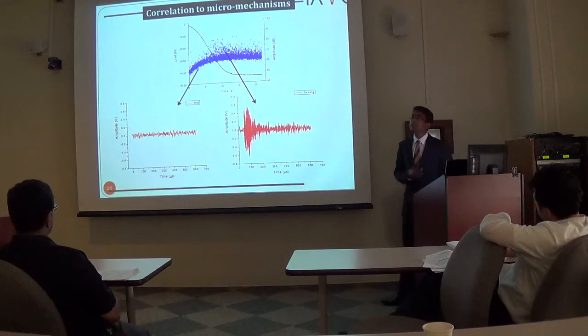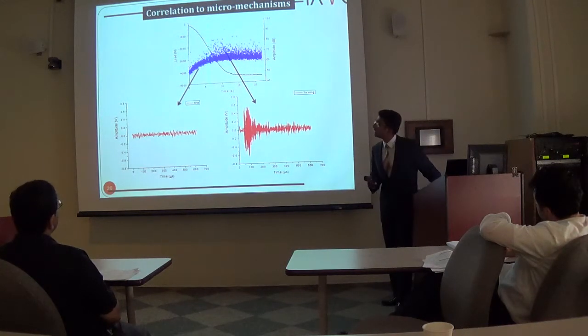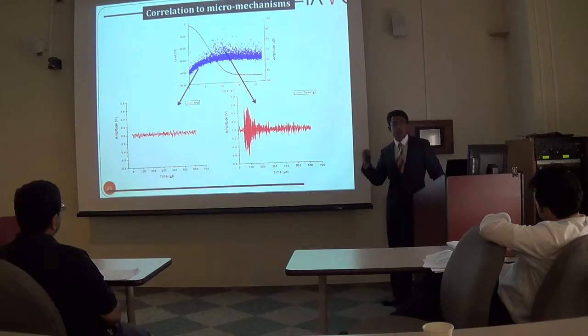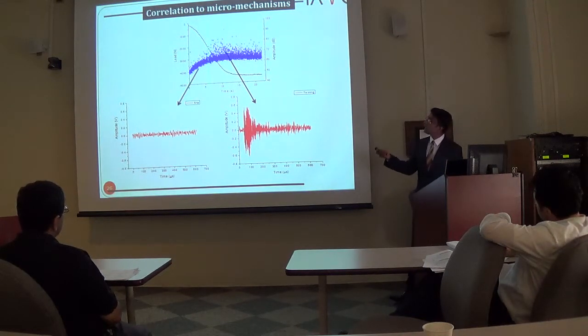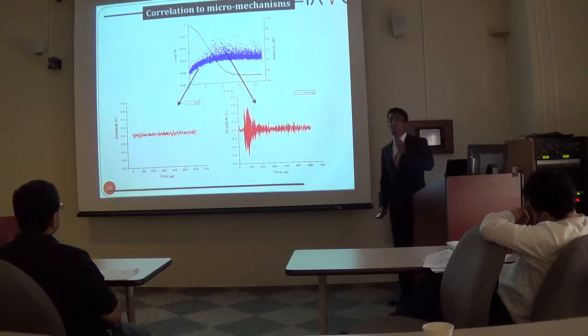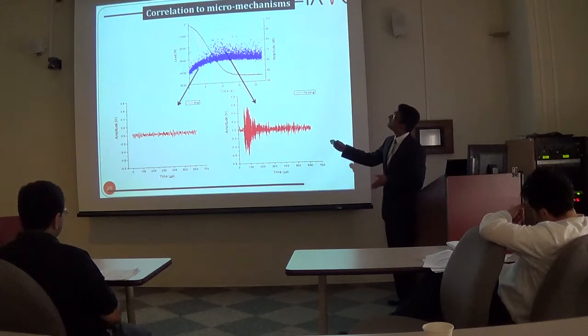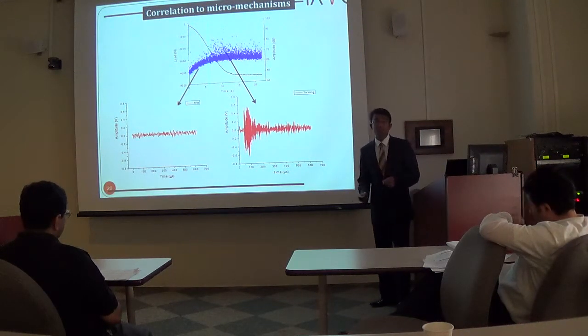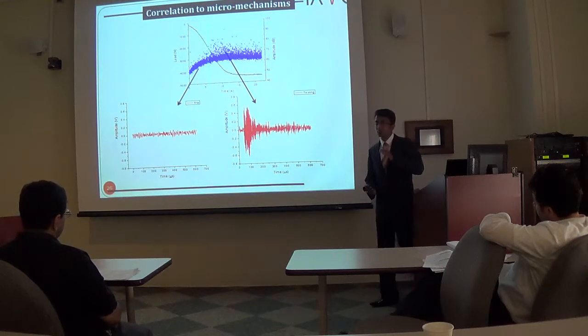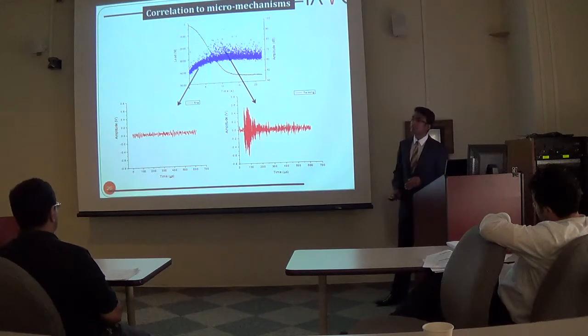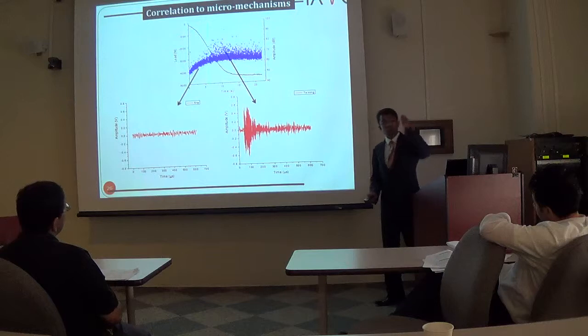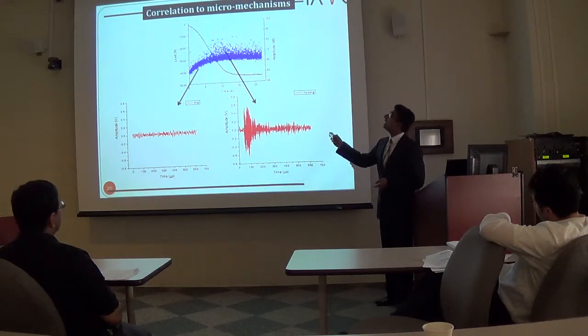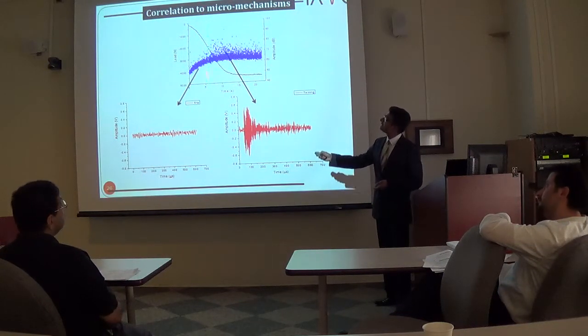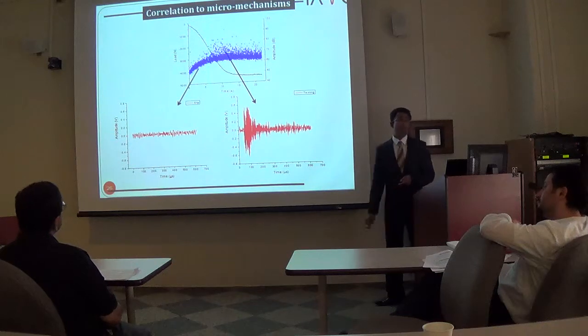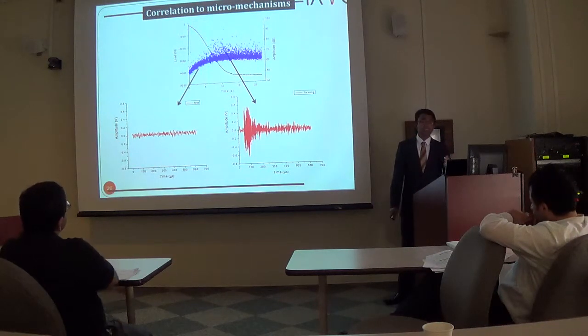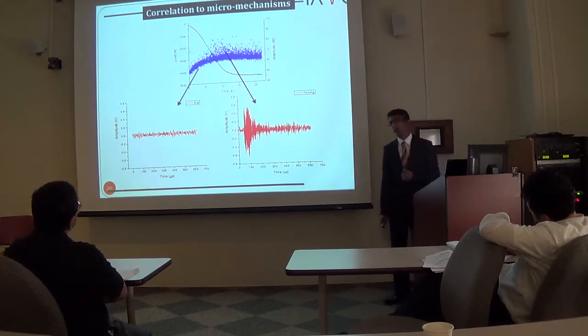Now, this test was repeated and the same phenomenon was observed. Thus, a future test was designed where the test was interrupted based on the activation of this AE amplitude in real time. So the specimen was tested, and based on the activation of these high amplitude signals, the test was interrupted. Now, it was seen that right after 6 seconds, we could see a change in the AE amplitude, as you note here. You can see the increase from low amplitude signals to high amplitude signals.